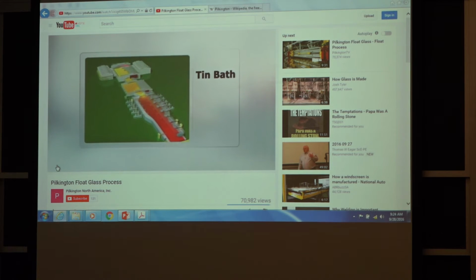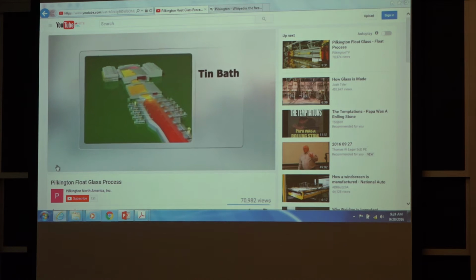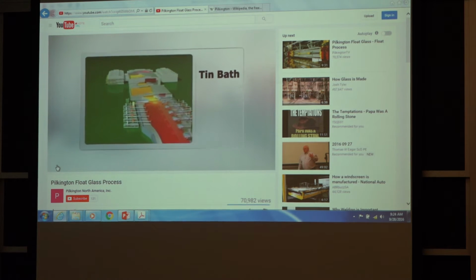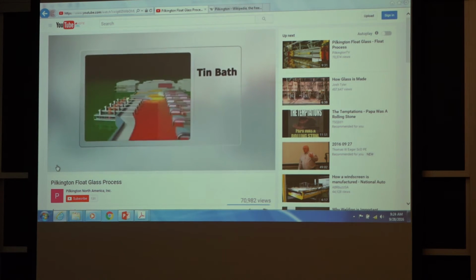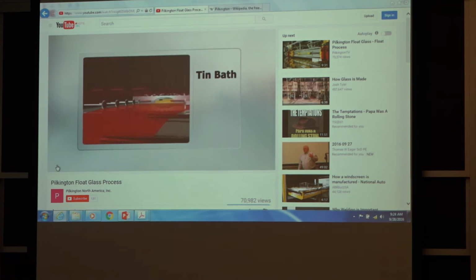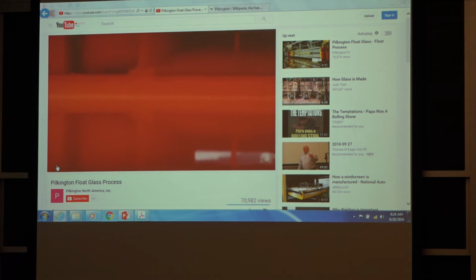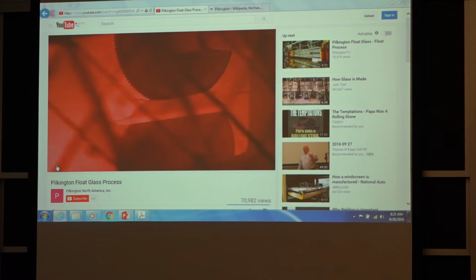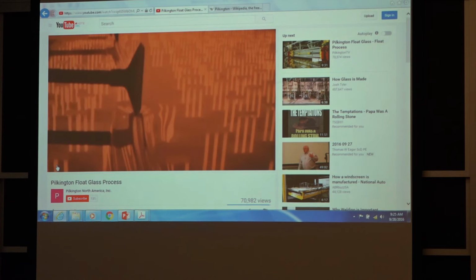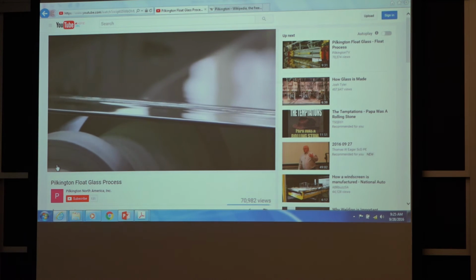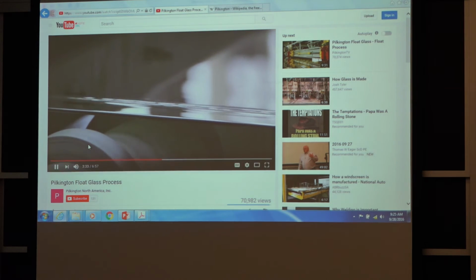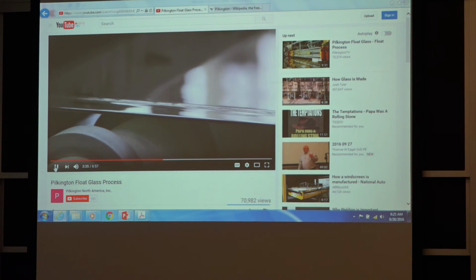Following the perfect flatness of the tin, the upper and lower surfaces of the glass remain absolutely flat and parallel with perfect spectral properties. So this eliminates the polishing procedure at the end because now you have very smooth glass. The top rollers controlling the width of the glass are sped up to produce a gentle stretching action. A controlled atmosphere of hydrogen and nitrogen within the bath prevents the tin from oxidizing. When it emerges from the tin bath, the glass is sufficiently hard so as not to be marked by the